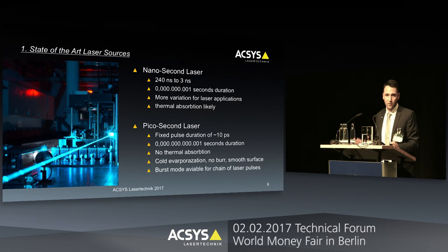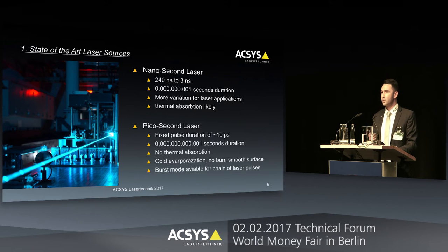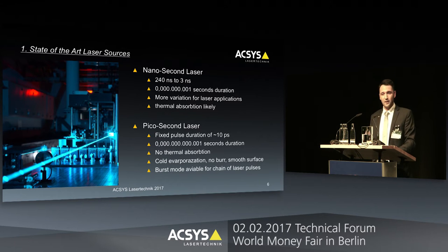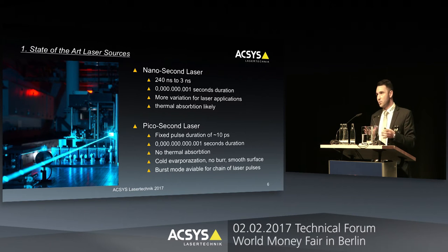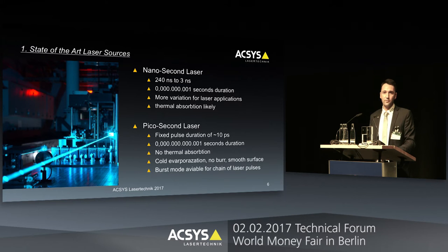We have two current state-of-the-art laser technologies to focus on. The first one is the nanosecond laser. It works in a range from 240 to only three nanoseconds pulse duration — a nanosecond being one billionth of a second. Because we can change the pulse duration and adapt it to what we want to do, this gives us more variation in laser applications. But even though a nanosecond is so short, it is long enough to create a thermal absorption and heat affected zone.